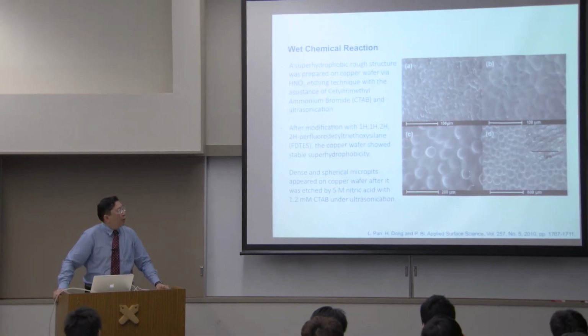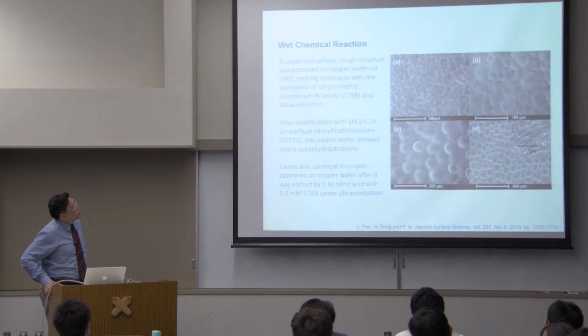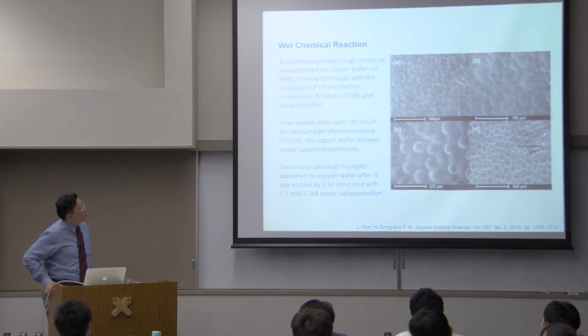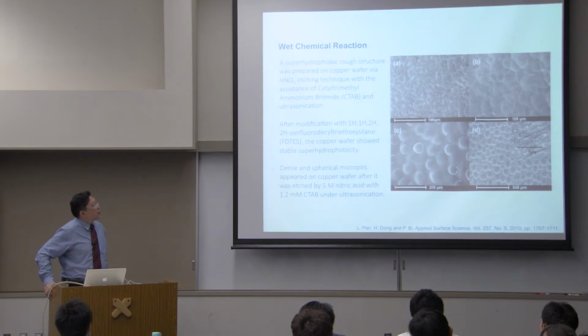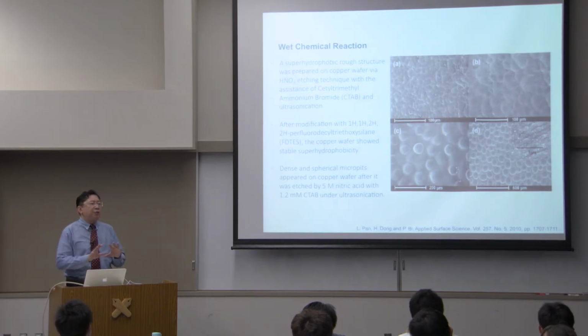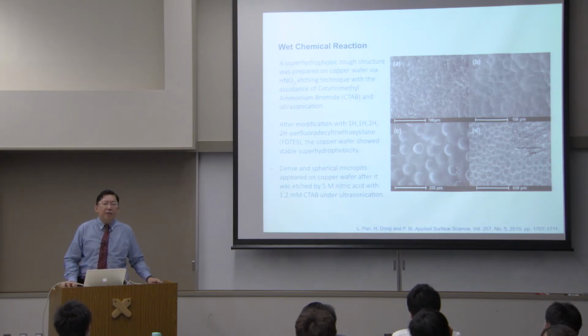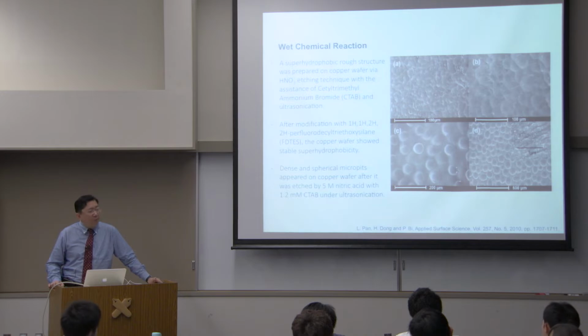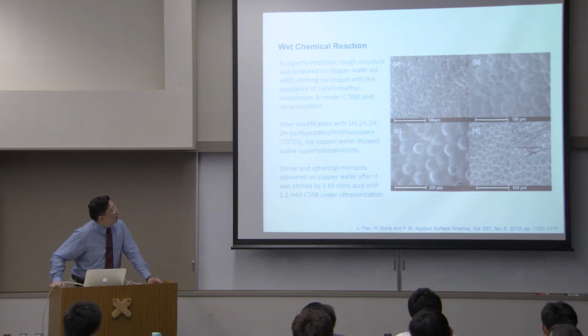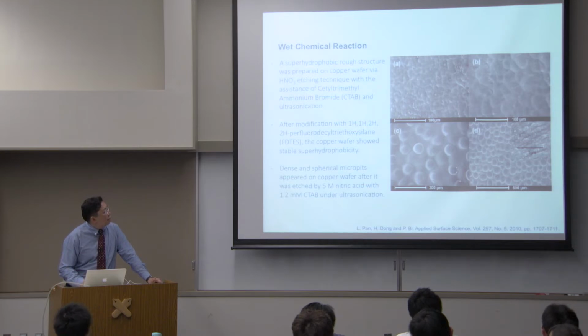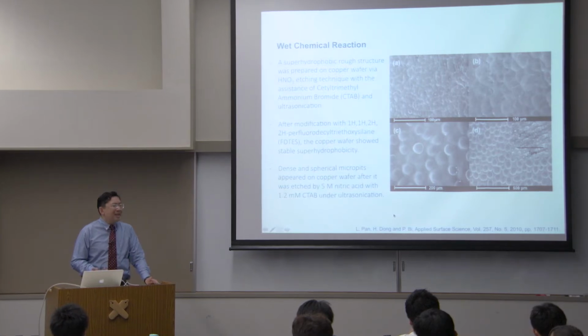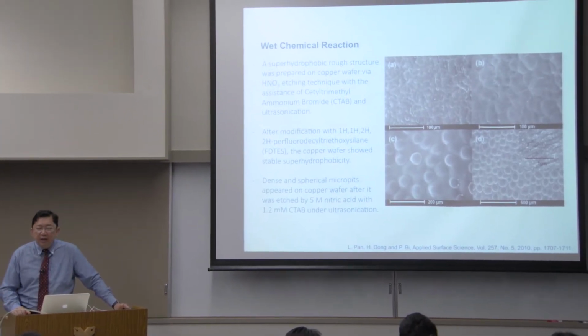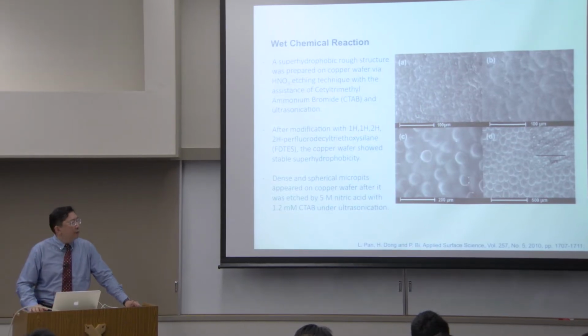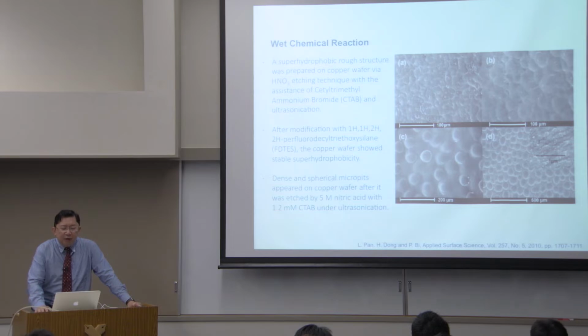Another method is based on wet chemical reactions. In this case, a superhydrophobic rough structure was prepared from a copper wafer via etching with nitric acid and a surfactant. The surfactant has the role of forming different types of surface structures, and the use of perfluorodecyltriethoxysilane (PFDTES) produces a low surface energy. So the combination of a surfactant and an etching agent such as nitric acid, and lastly the modification with a fluorinated silane agent, makes it superhydrophobic.